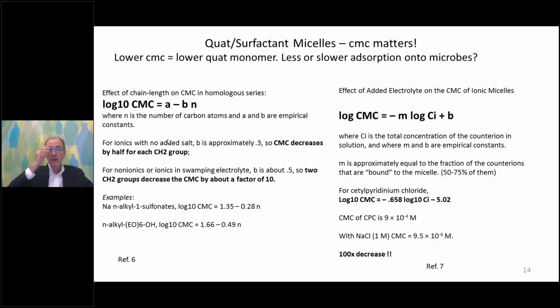And then on the right, electrolyte matters. For many of our formulations, we need to buffer them. EPA is concerned about pH, and so we'll be adding electrolyte. And adding electrolyte, as we know, can also decrease CMC. The equation on the right reminds us that the log of the CMC scales as the amount of bound counterion and 2 constants, which is directly related to any additional salt that's present in the solution. So an example there would be cetylpyridinium chloride, which is a quat. Its CMC can be reduced by 2 orders of magnitude by adding enough sodium chloride. CPC, by the way, is a very useful quat. That's in your mouthwash.